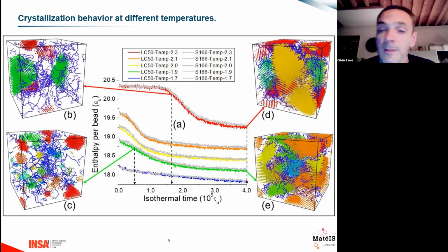So here we performed a lot of tests with this same technique. This is an example with a different system, among a lot of different systems with different chain lengths. Here it's a mixture between long chains and short chains, and we just checked whether the crystallinity was comparable to a classical system, but it's just to show how it works. We have the enthalpy and the isothermal time, I mean the time spent at a given temperature to favor the crystallinity.